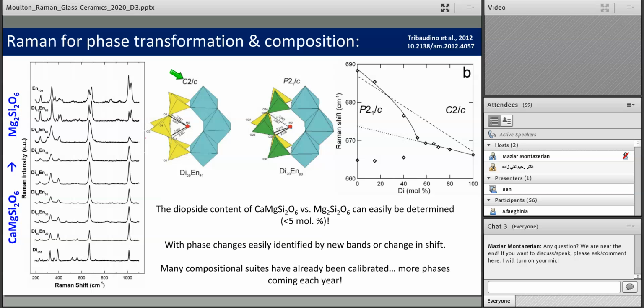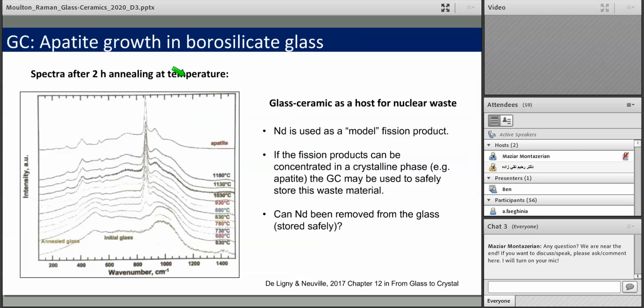And during this reduction in symmetry, you can see here it happens around 50% of diopside, you have a splitting. This is quite obvious in the spectra. And when you see this band splitting, you have this phase change with different symmetry that we've discussed. So if any of you are studying phase changes and you know what the Raman spectra are of the two different symmetry phases, Raman is extremely sensitive to these situations.